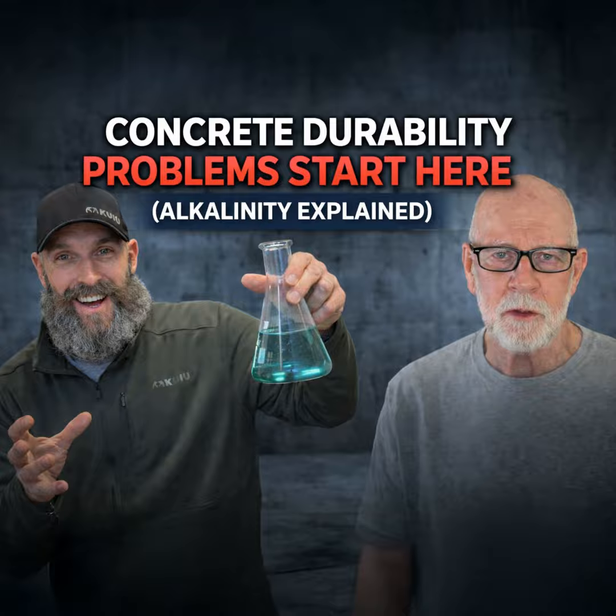But if you move it to the tide line and you look at piers, where's all the damage? At the tide line, where the water goes in and out. The more movement of moisture you have and the more allowable moisture over time, that will damage the concrete. So porosity and permeability are both bad news. We can produce concrete that doesn't have either, but we're not being allowed to, because all we have to do is hit the compressive value standard. That doesn't tell you anything.